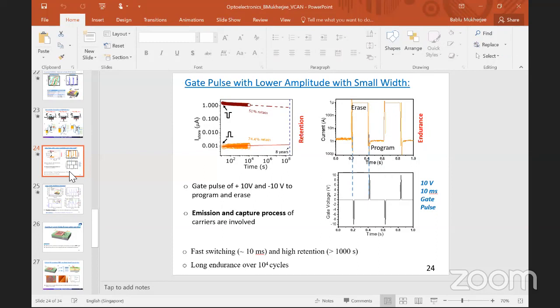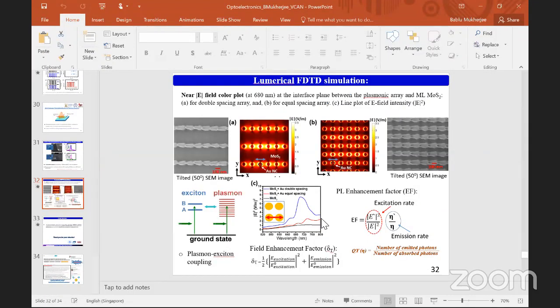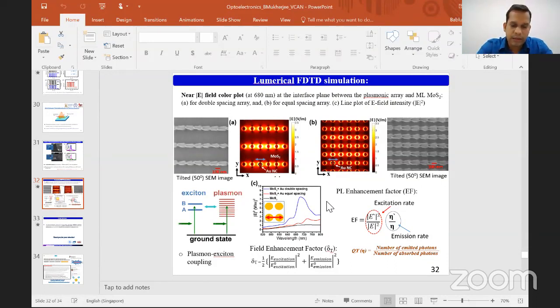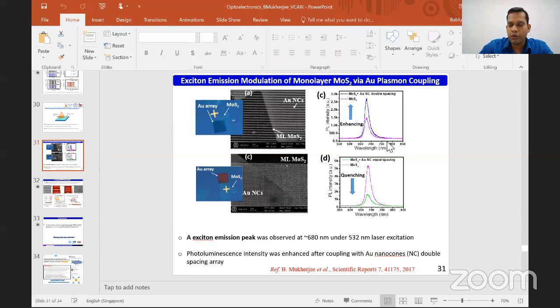Another question is from Sinu Matthew, about MoS2 plasmon double spacing enhanced PL. The line shape of the main peak seems to have many components. So how about the trion plasmon interaction? Any idea on this? Yes. Of course, there can be trion formation also, depending on the laser power we use, and sometimes we use bias to make a charge, and that also gives rise to trions. But in our study, if you see the photoluminescence spectra, we do not have such information. For trions, the full width at half maxima of the spectra will be much bigger, and there will be at least a small shoulder. Here we do not see that much, but we do not have a direct study on that transformation. Maybe we can also extract some percentage.